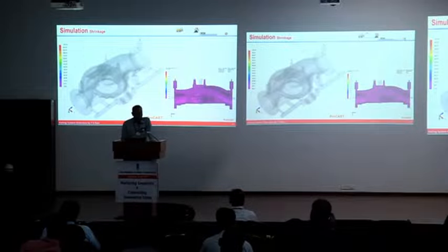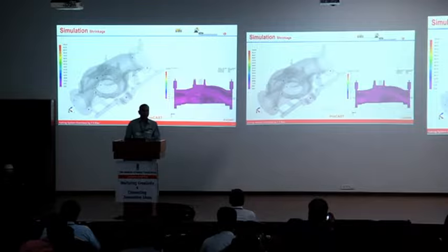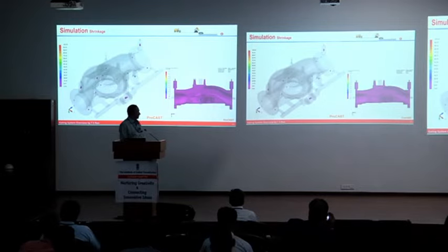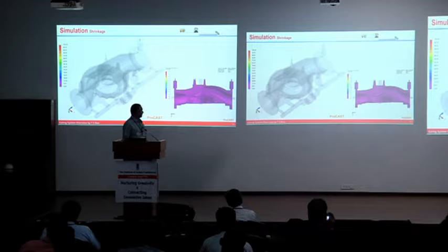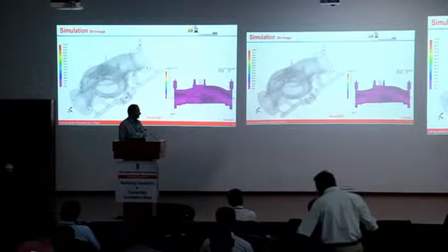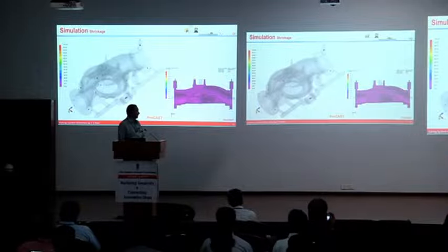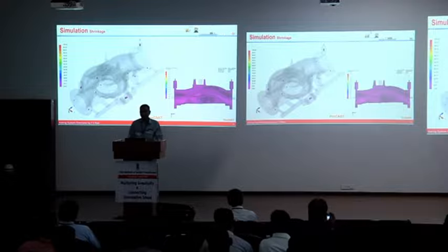Then the shrinkage. When the casting is getting solidified, we can see the hot spots in the casting. Again, the hot spots can be defined with respect to the graphical form, like this, divided from 0 to 100, as level 1 to level 5. The first 20 is considered a level 1 radiography defect level, up to 40 is level 2, up to 60 is level 3, up to 80 is level 4, and 100 is level 5. If you see the casting cut section, we can make out from the cut section color that the whole casting is well within level 1 or level 2. So this is the indication that we can find out.